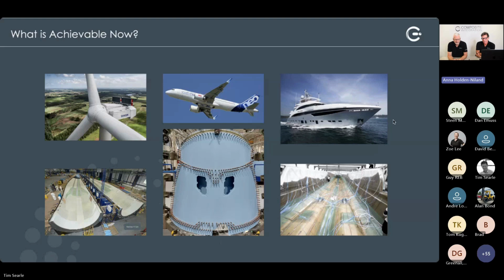Aerospace grade laminate quality was evident, with fibre fractions just shy of 60%, and a void content that's now becoming so low that it's actually challenging to measure, and quite often the reports get sent back to the lab because we need to try them again because the quality is so good. And in addition, there's a significantly lower overall manufacturing carbon footprint without the use of the autoclave. And this is an example where it's very viable as an alternative to pre-preg.